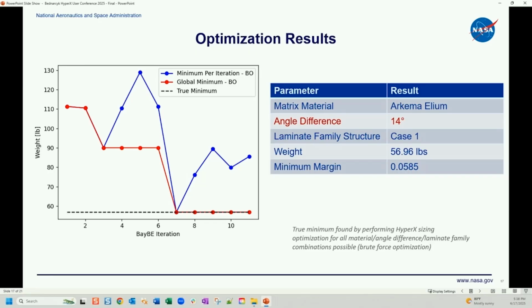And then it decided to check a point that was not as good. So the weight from the next iteration went back up to 110. So it obviously didn't take that as the global minimum. So the global minimum stayed the same. Then it went up again, so the global minimum stays the same. Came down. Global minimum stays the same, and then basically after the 7th iteration, it found the minimum. Okay. It tried some more before we stopped it, but you see it was interrogating areas that weren't as good. Okay, so after 7 iterations, it pretty efficiently found the optimum.